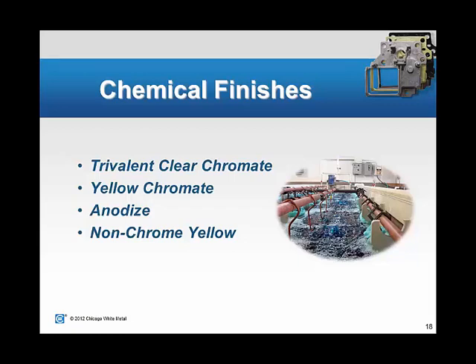In all of these, like I mentioned before, the chemical makeup of the surface of the die casting is actually being changed. So one of the benefits of these coatings is that there's really no added thickness to the part. So for parts with complex features or tight tolerances, there's basically zero added thickness, which is a good side effect for this type of finish. All these finishes provide additional corrosion resistance over a raw casting. They also, like the previous batch of options, provide a proper surface preparation for any coatings that come after it. Again, we would consider this not a cosmetic finish, but it can be used as a final coating if that's all that's required. Many of our customers do use these options as a final finish.